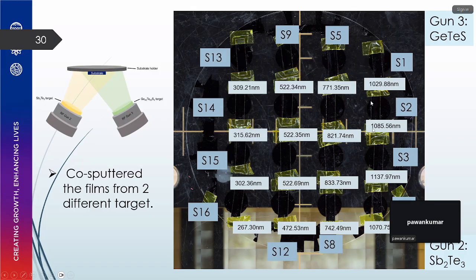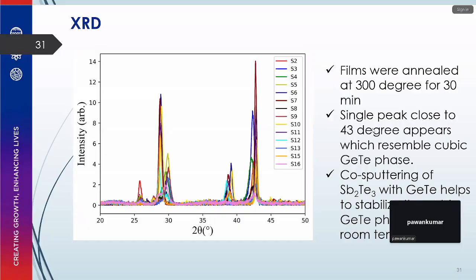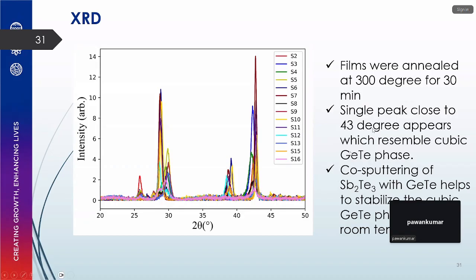The value you see here is the thickness of each circle. Each circle is one composition of the film. Once we had done that, we performed XRD of these films. I don't have the full Rietveld analysis, but the initial stage showed that when you co-sputter these films, we somehow stabilize the cubic germanium telluride at room temperature. Instead of going to 400 degrees Celsius, we can get the germanium telluride cubic phase, because we see a single peak around 43 degrees here.